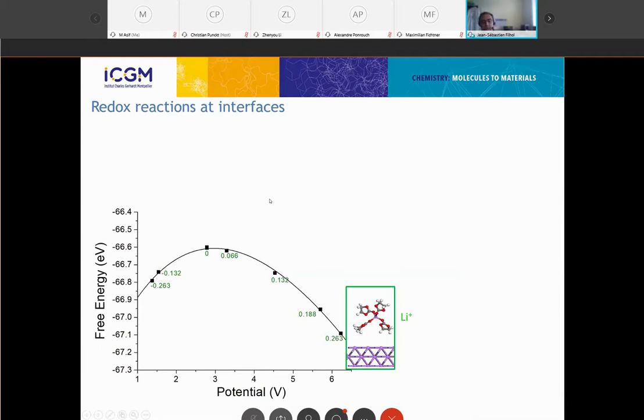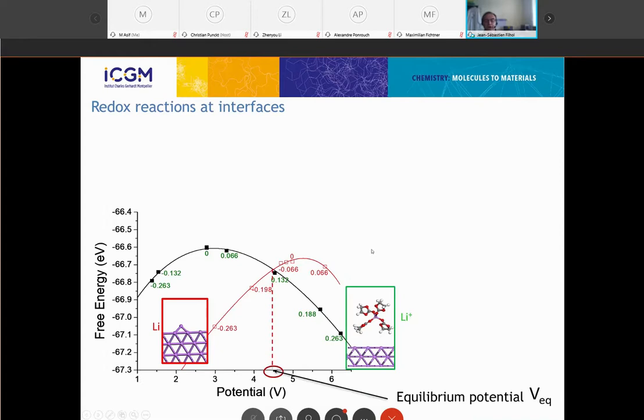So next, in my little tutorial, how do we model electrochemical reactions at an interface? In fact, we need a redox pair. We have some species that will react as the oxidant, for example, some kind of A plus over the surface. And we will need another interface that will be the reduced interface, in this case, for example, lithium that will be deposited on the surface. And when we have computed that, we can extract the electrochemical reaction.